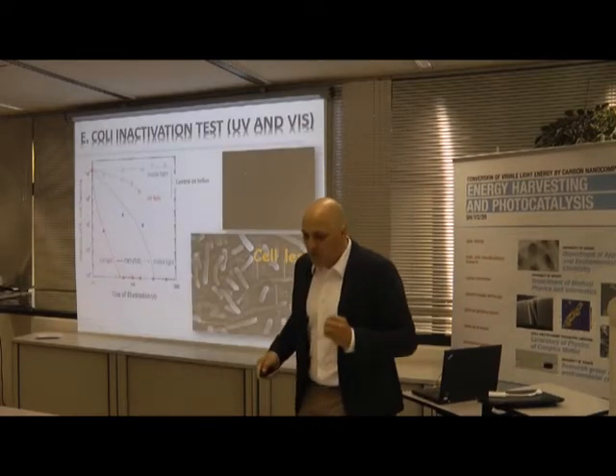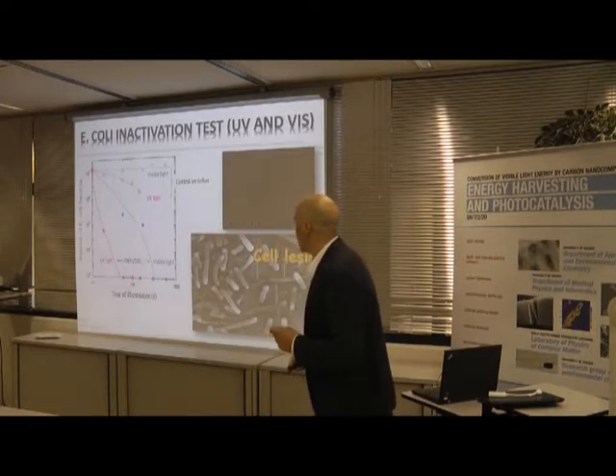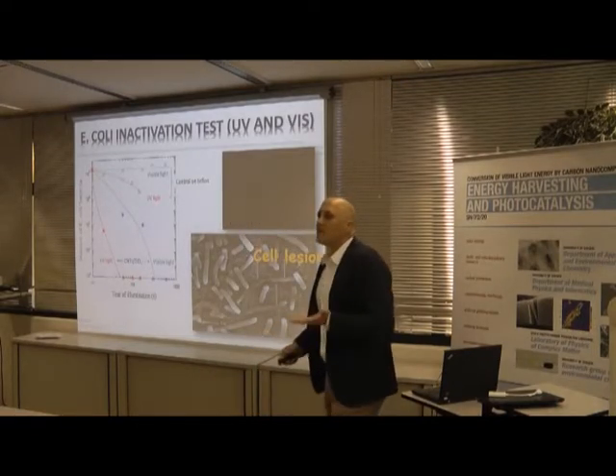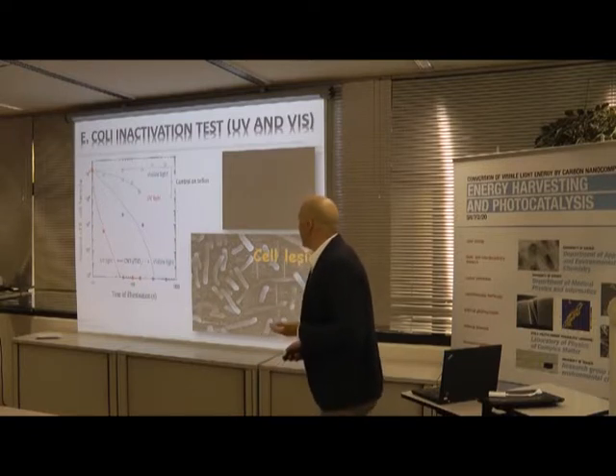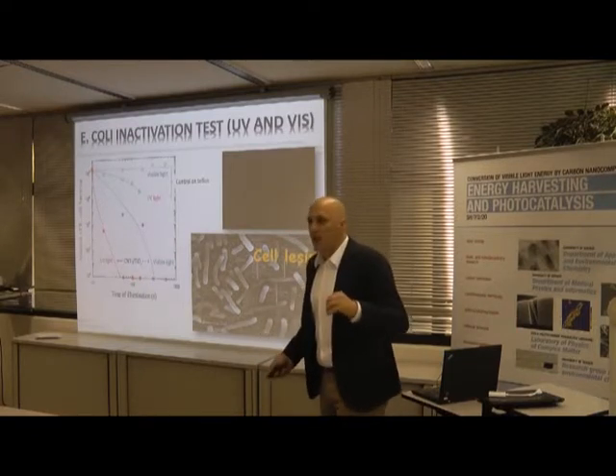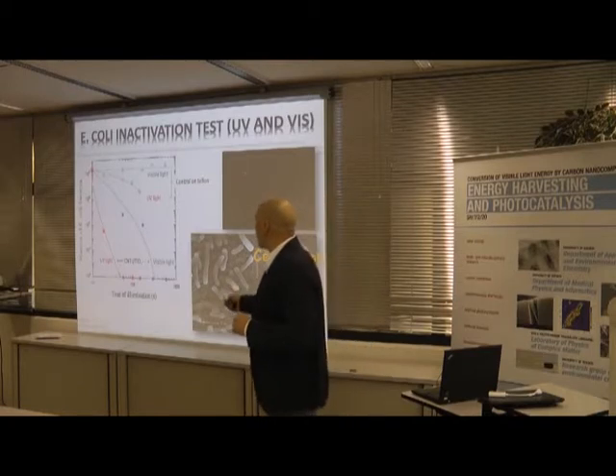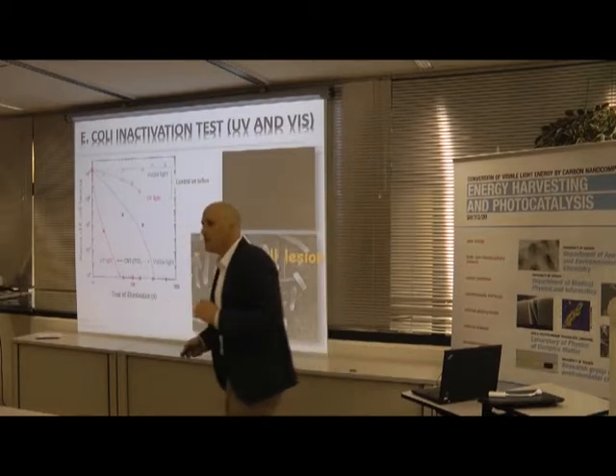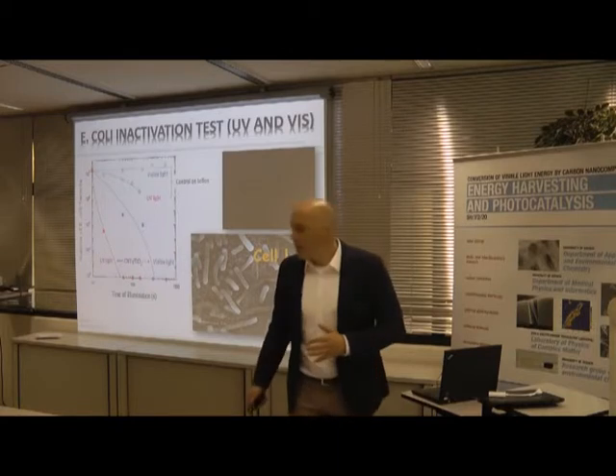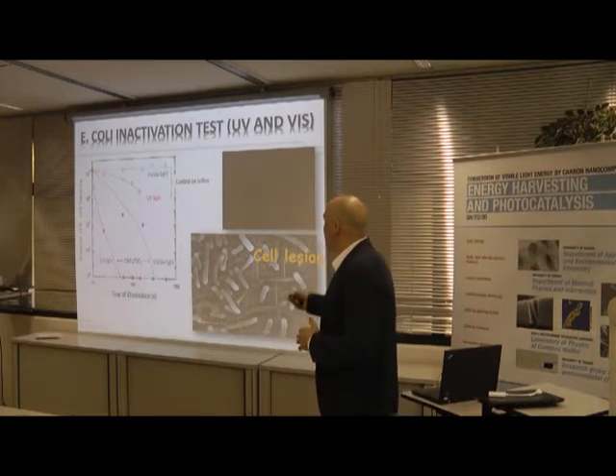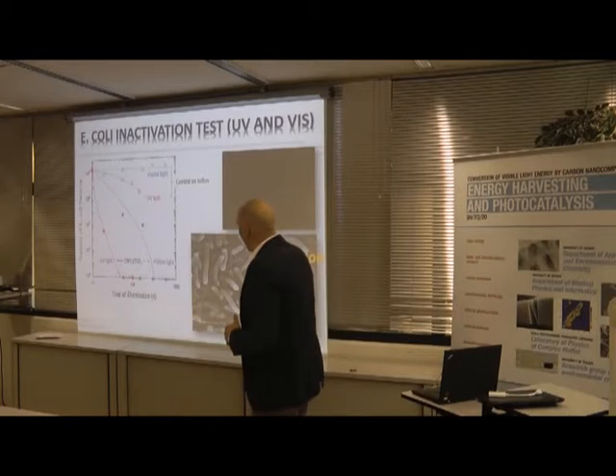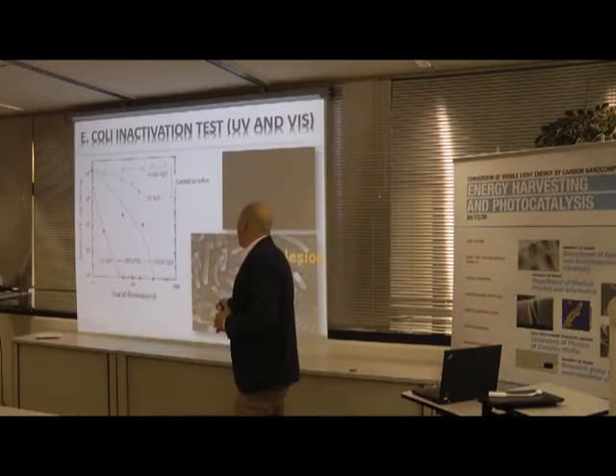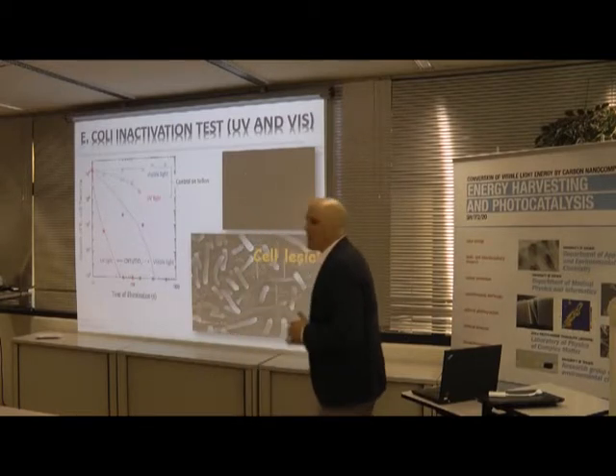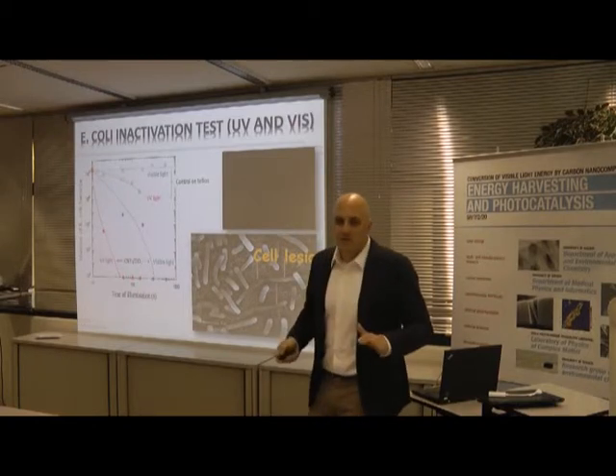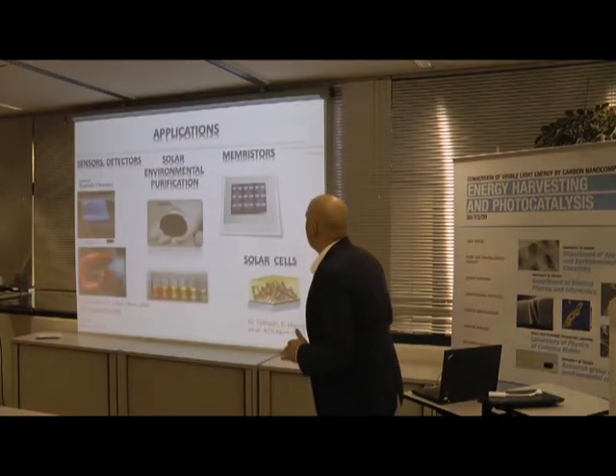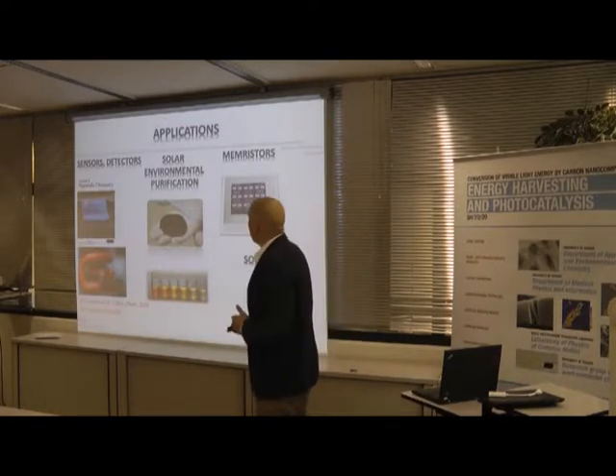If you want to purify water or air, you need to test your material. What is the sterilization efficiency? And we tested by using E. coli bacteria, and what we have found is that our composite successfully killed the E. coli bacteria with UV light, but surprisingly with visible light as well. So for visible light, we needed like 2 minutes, for UV light 15 seconds, and there was no countable bacteria on the surface. So that was about solar environmental purification.